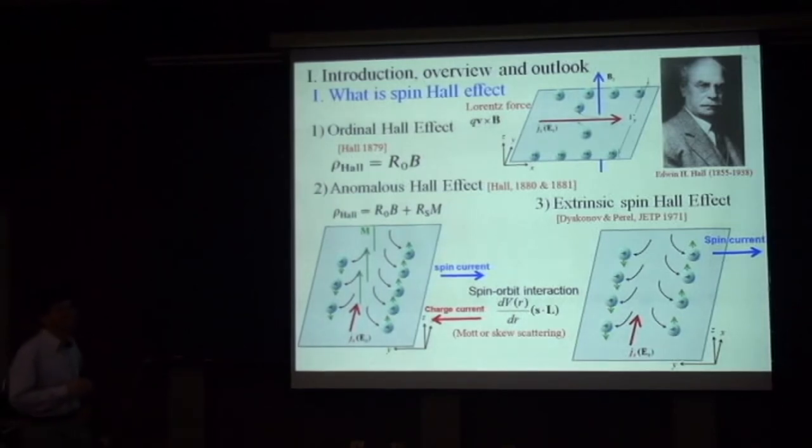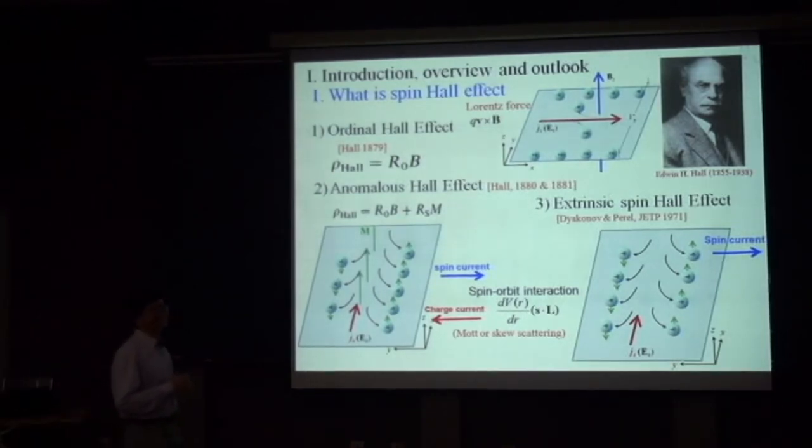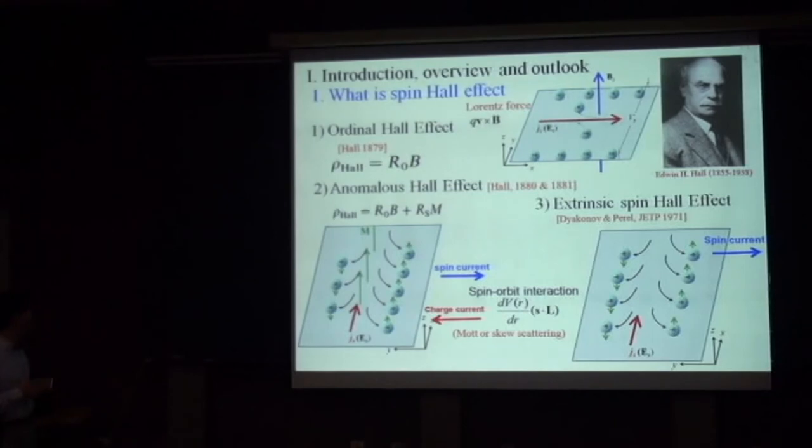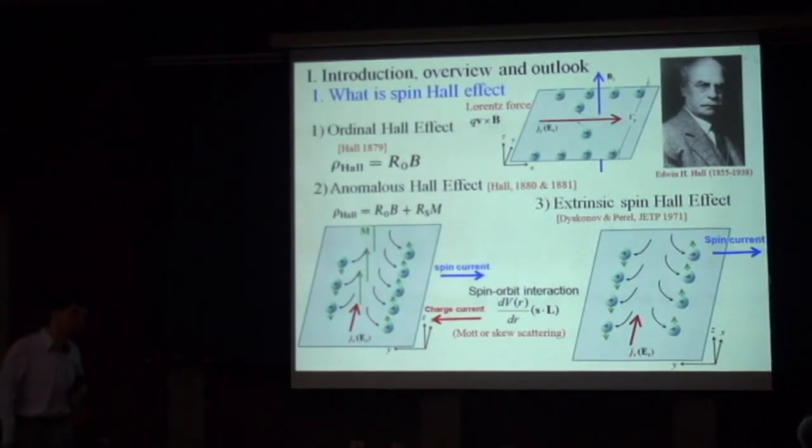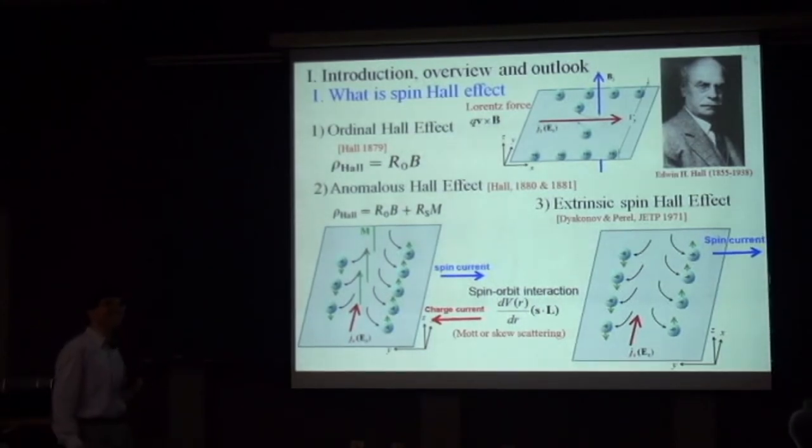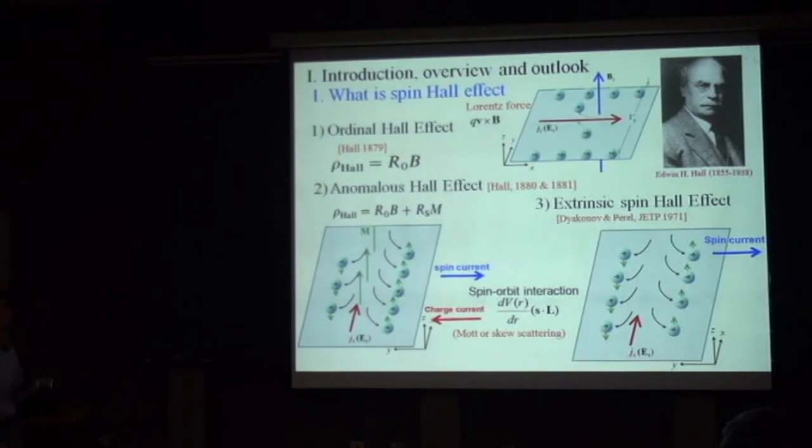You are always an expert. The first question is that, you do need magnetic impurity. Not necessarily a ferromagnetism, but you need the impurity has a local moment. And, in order to have multi-orbital Kondo effect. So you need the valence shell, like a d shell, which is partially filled. So with these two conditions, it might have a multi-orbital Kondo. Now, the second question is critical. Actually, I took my sabbatical leave last semester. And I spent two months with Ingrid Mertig's group. And she is the one that did the calculation you mentioned. But, they have also a story how this giant spin Hall effect occurred. And their theory is that, if you dope gold with a light atom. But the potential difference is so huge. Because if you have gold, which is big and large and heavy, if you dope with nitrogen. When it's small and tiny. Now, imagine an electron passing through this kind of impurity. You will also feel very strong scattering potential.